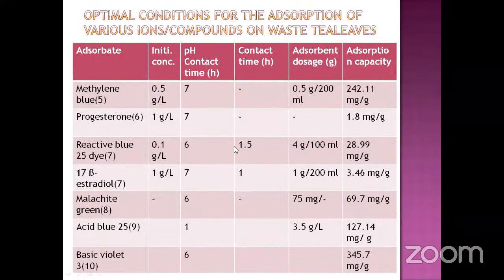And this is some of the data which I had collected. Actually, the data was very huge and it cannot be accommodated in a small presentation, so I made it into a small table form. The methylene blue was analyzed in the reference, I had quoted the reference. With the initial concentration of 0.5 gram per liter, pH 7 is the maximum adsorption, and adsorbent dosage 0.5 per 200 ml.